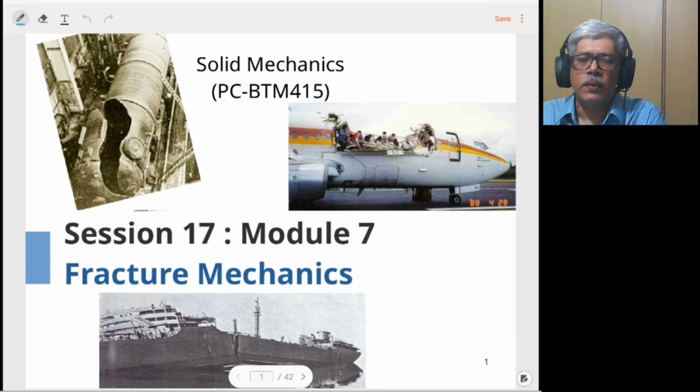So you obtain the stress intensity factor for your component in the presence of the given loading. If possible, you can superimpose different combinations of the loading and then compare the resultant stress intensity factor against the allowable, that is the plane strain fracture toughness of the material or K1C. By using this basic equation, one can obtain the allowable loads or the acceptable geometry or the acceptable crack dimensions for your problem. So that concludes this session.